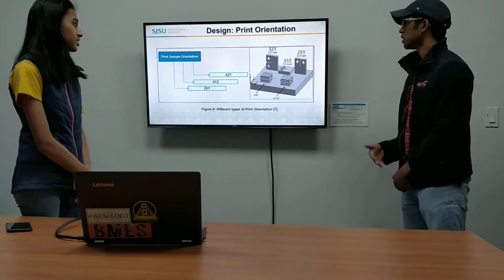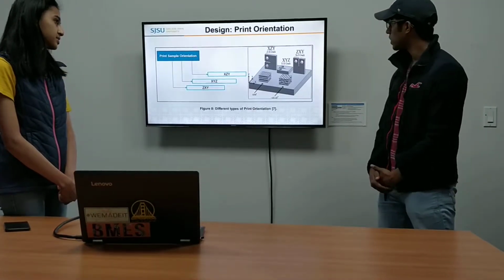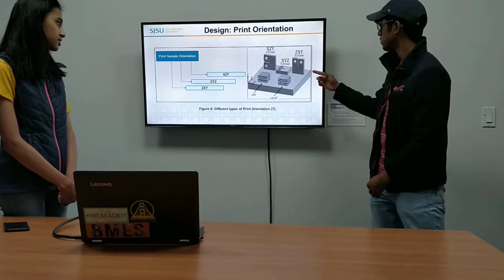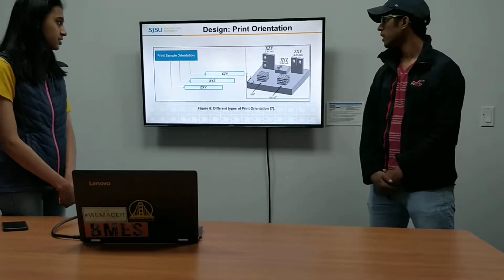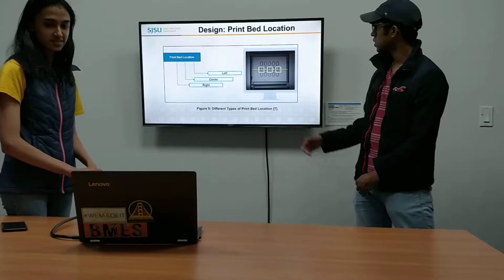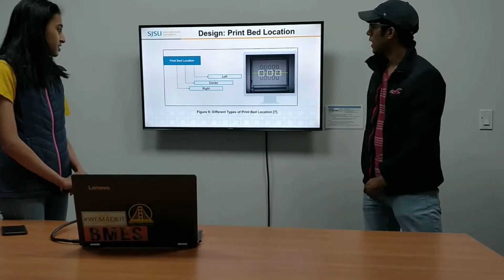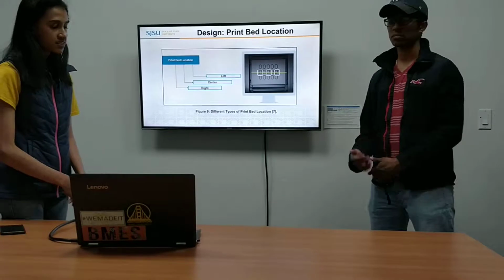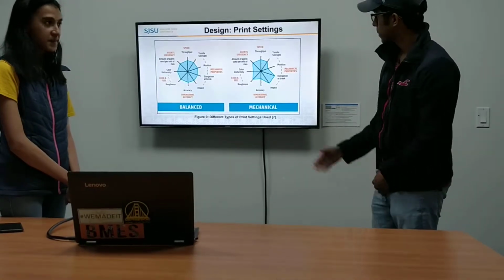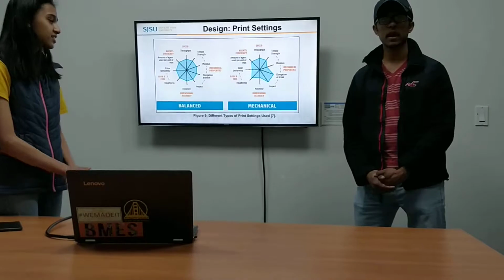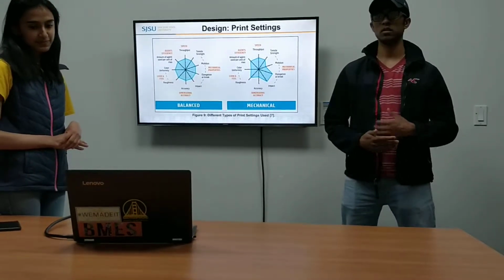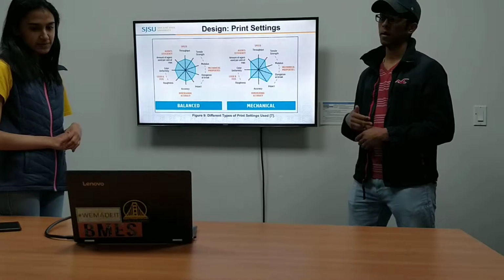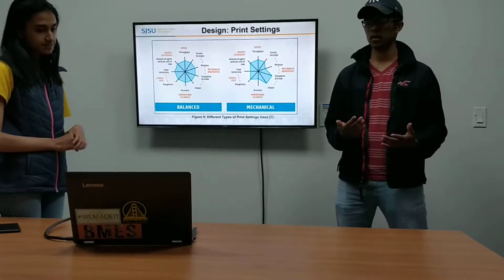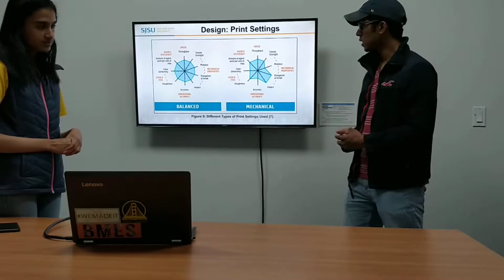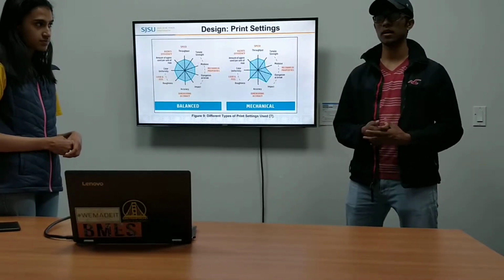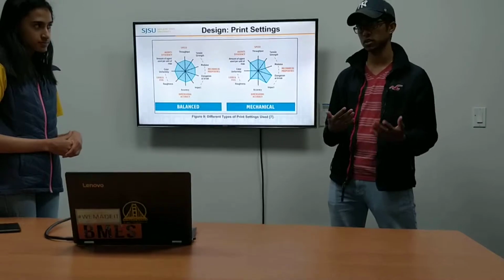This is a diagram for the print orientation. These are the orientations for ZXY, XYZ, and XZY. And these are the locations. So this is the print bed, and left, center, right. That's how the specimens are going to be built. And for mechanical and balanced, mechanical is a faster print, so the mechanical properties of balanced are going to be better than mechanical, and that's a known fact. But we're still using these settings just to see how fracture toughness compares for these 2.